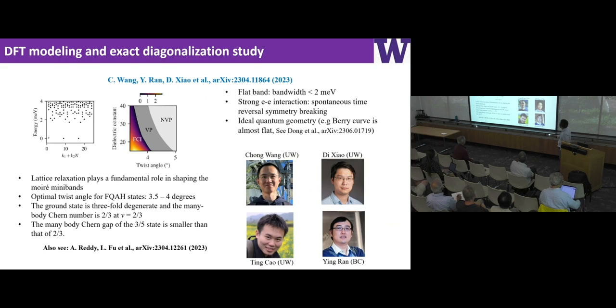And what we learned is why it's wrong. What they found is that lattice relaxation actually plays a really important role in shaping the Moiré minibands. That's how you determine the twist angle. He found that the optimal twist angle for this FQAH effect is between 3 to 4 degrees, so we basically got lucky to make such a sample at the right angle. Then he also did a calculation of these many-body Chern numbers, 2/3 and 3/5. He found that the gap at 2/3 is slightly larger than at 3/5.